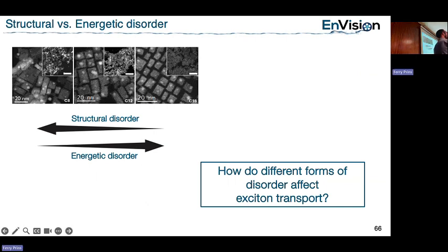You will relate that to the energy disorder. Yeah. But obviously, especially on the larger scale, you see that there is disorder in the distances as well. And of course, it will slow down the diffusion when you have to reach particles which have fewer neighbors or more distant neighbors. So you must also take into account the distribution of distances. Yes, this is interesting. And not only that, this will also be influenced by the distance dependence of the energy transport. There are some old theories, by Förster, Hirayama or someone, which describe the distance dependence of energy transport due to multiple interactions, for example.